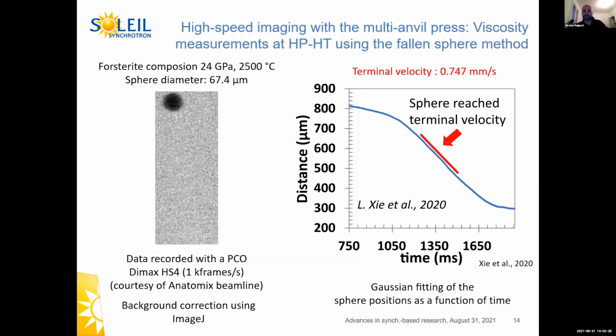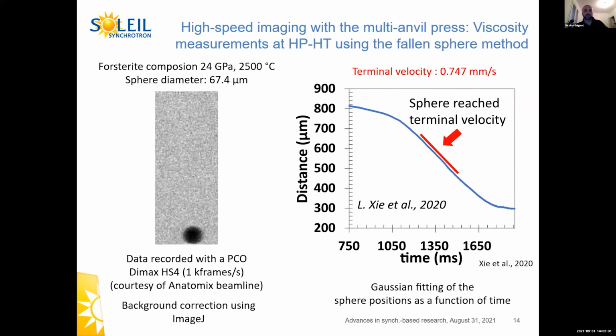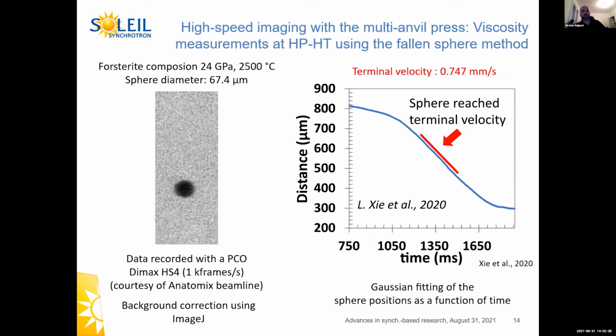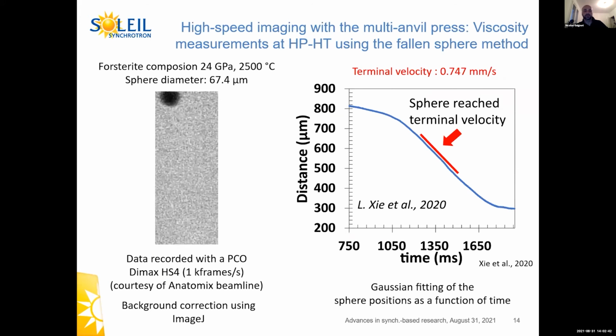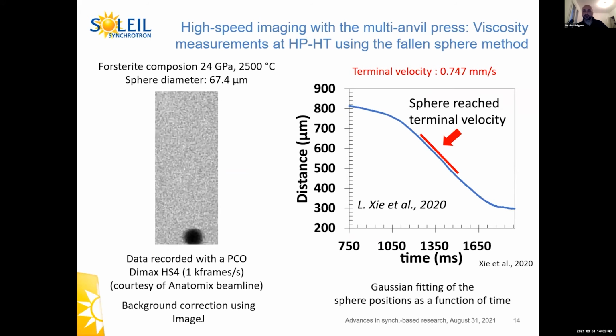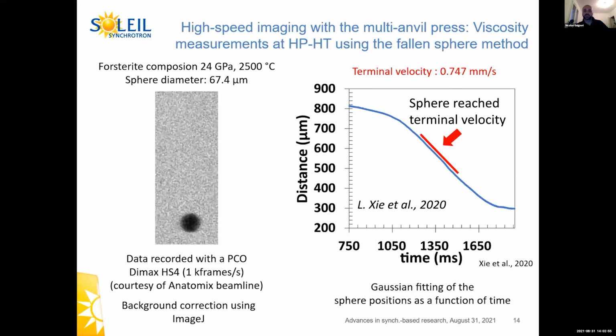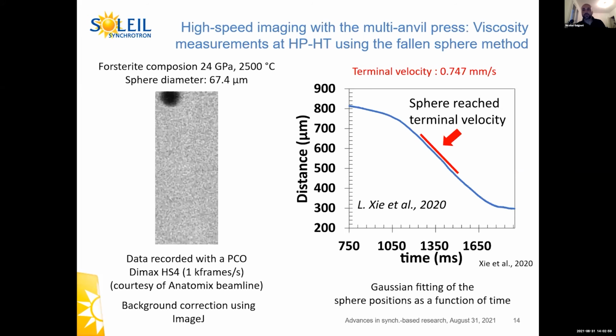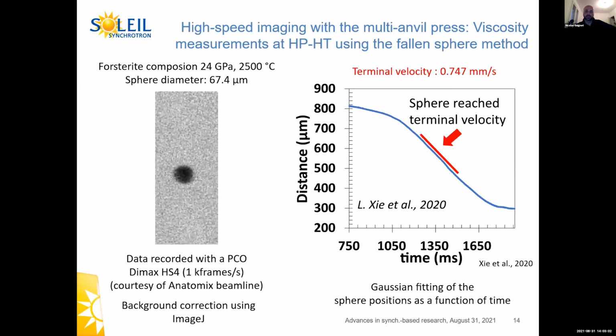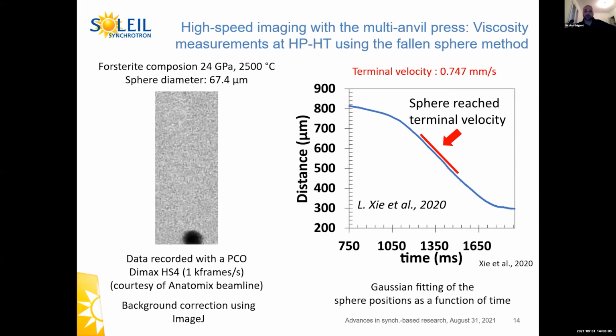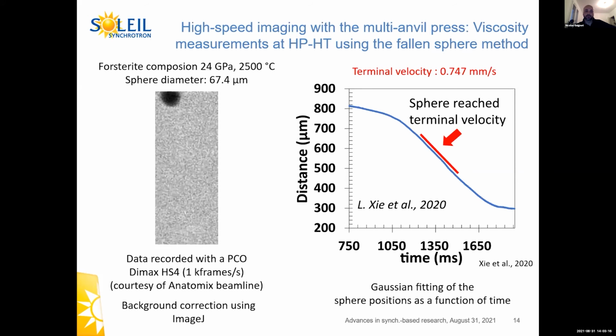Next, this is not tomography, but still high-speed imaging. Here I'm talking about high-speed radiography that is adapted to the multi-anvil press. In this case, these are viscosity measurements done at high pressure and high temperature using the falling-sphere method. Here, the authors, Xie and collaborators, managed to do these measurements at very extreme conditions for this type of measurement. I'm showing the forsterite composition, 24 GPa, 2500 degrees C, recorded at 1000 frames per second, thanks to the high flux of the pink beam. The terminal velocity of the sphere is used to get the viscosity of the melt. And this has very interesting implications for the crystallization regime of the magma ocean.